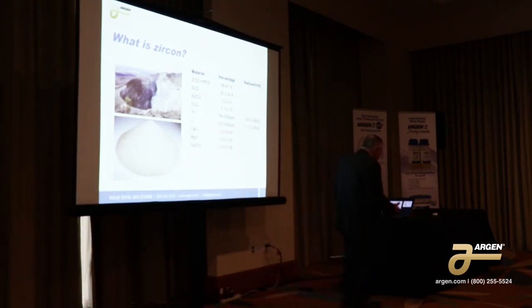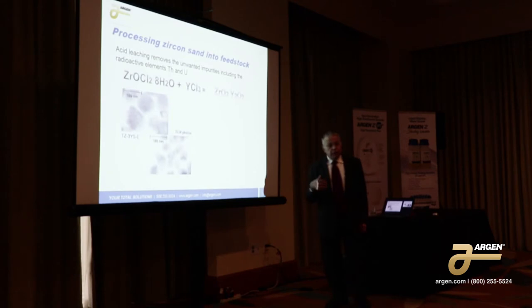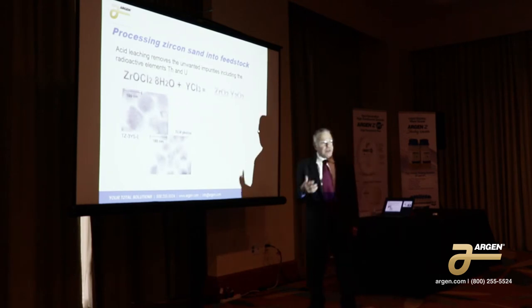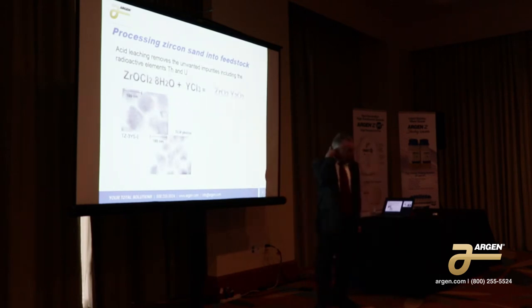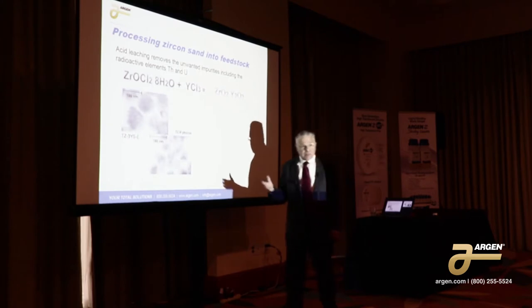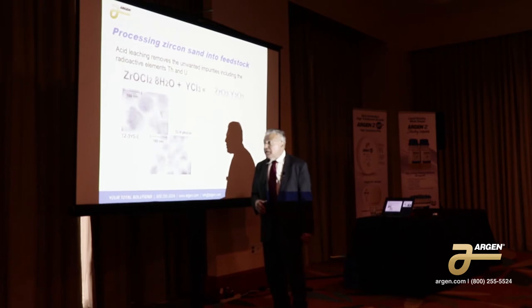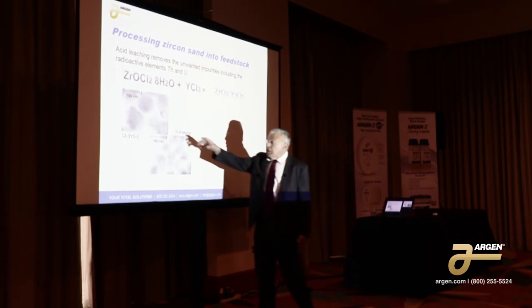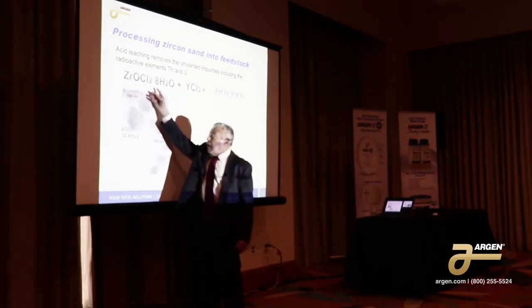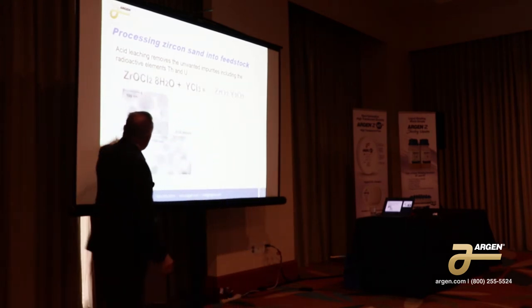These obviously have to get reduced substantially from fairly high values. There's an alkaline process and an acid process. Right now, the majority of the materials made for dental zirconia uses an acid process. So the material gets dissolved in hydrochloric acid and water — it's a hydrothermal process, meaning it's in water. It's a water-based solution and then we apply temperature to it. So the zirconia forms a chloride — this is zirconium oxychloride. And it's a commodity.